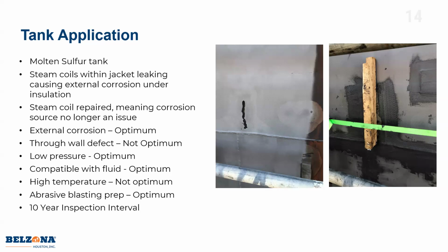The through wall defect, that's not our optimum. Anytime you're repairing a through wall defect, you now have a chance for the composite to fail, theoretically. Low pressure is optimum, and it's compatible with molten sulfur. High temperature, that's not the optimum. Abrasive blasting is optimum. So this, we gave a 10-year inspection interval.